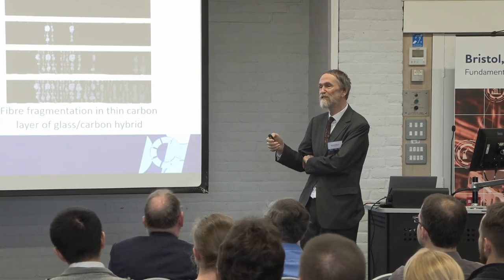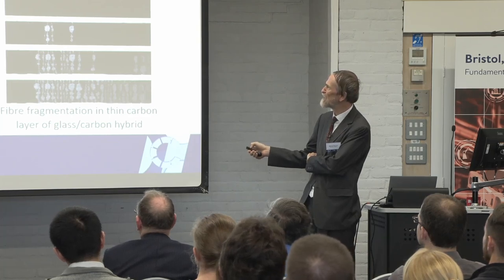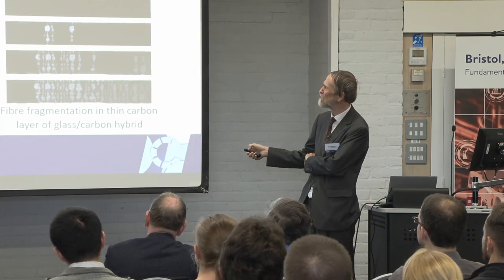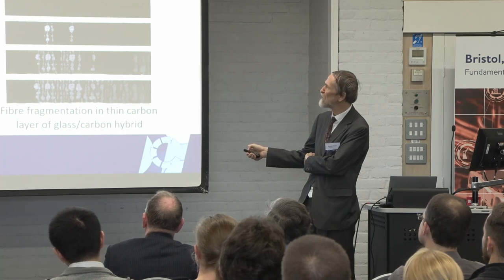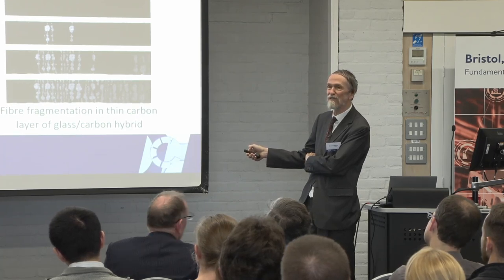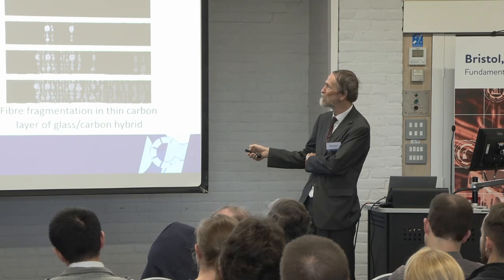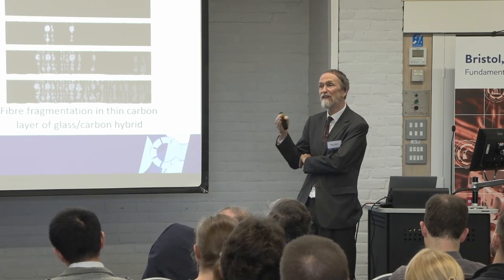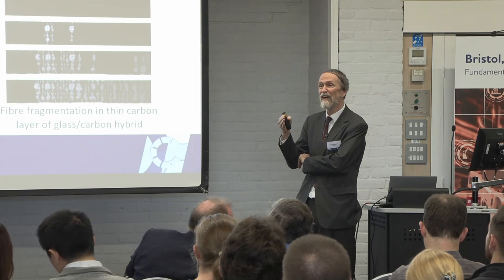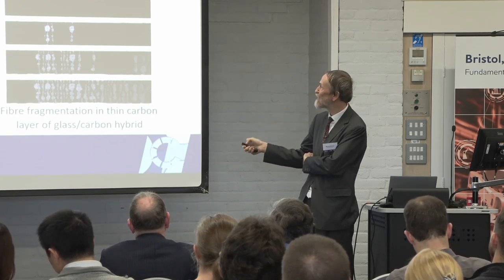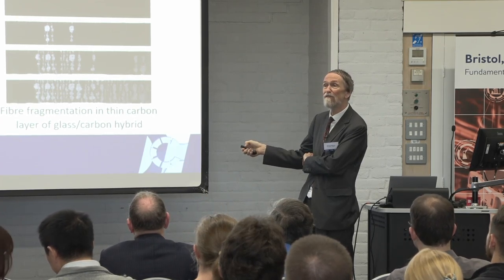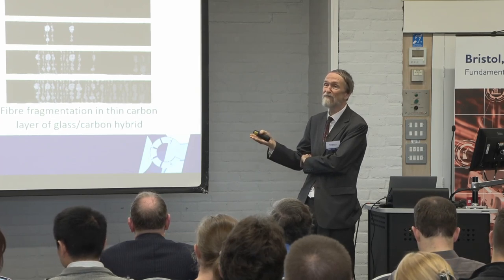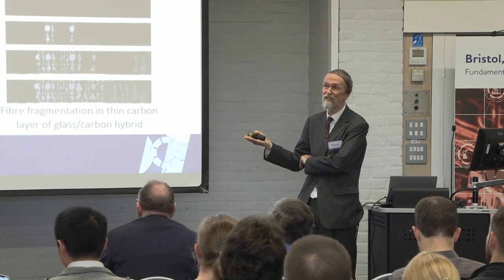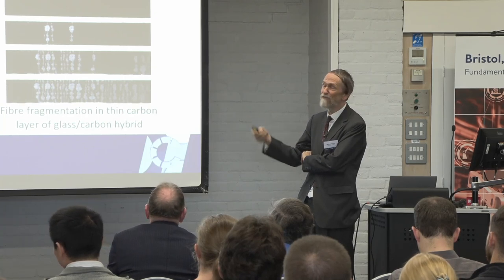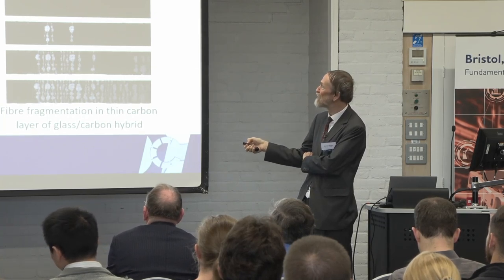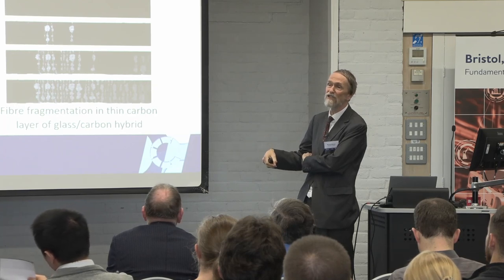So what actually happens is that this is actually an angle ply, but it's very similar to a hybrid. So at this point here, when you get this knee, that's when the fragmentation starts to develop. And as you go along this plateau, the fragments are developing. And we have measured the fragment density, and you get more and more fragments occurring until you reach a saturation. And when you've got a fully saturated fragmentation, in the same way as you do with a single fiber fragmentation test, it's the same thing at a different structural level, then it becomes saturated, and then you start to see an increase in the stress again.